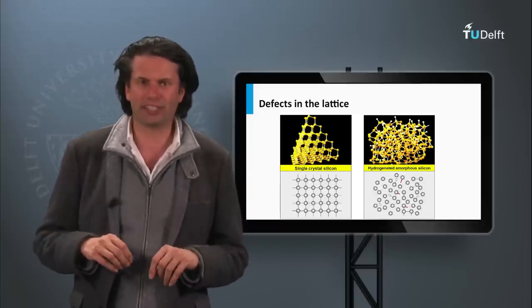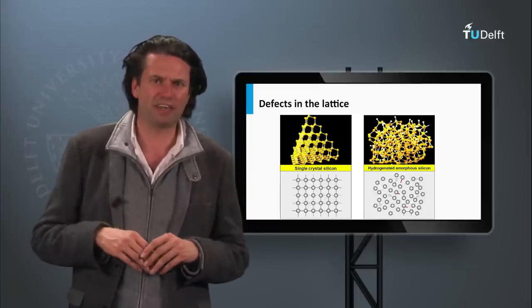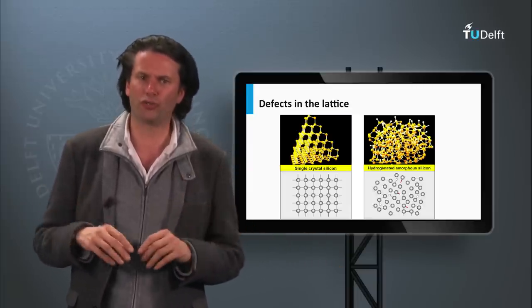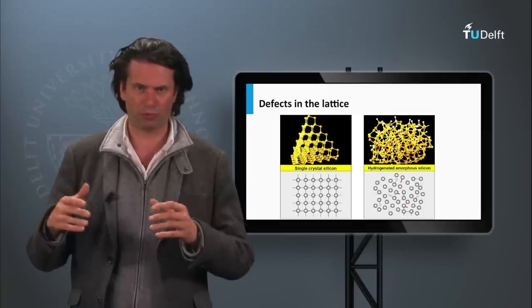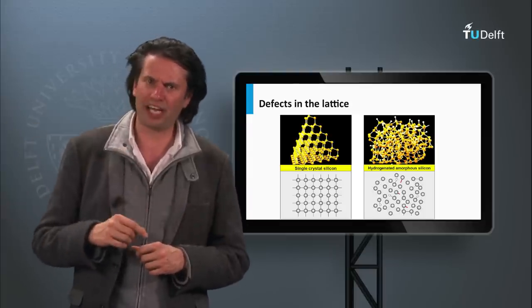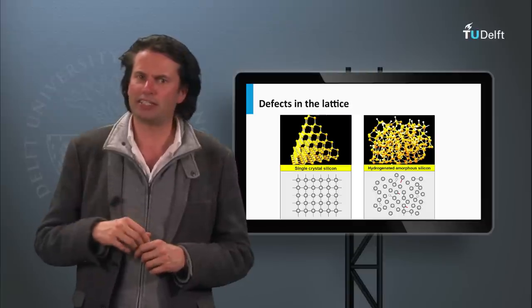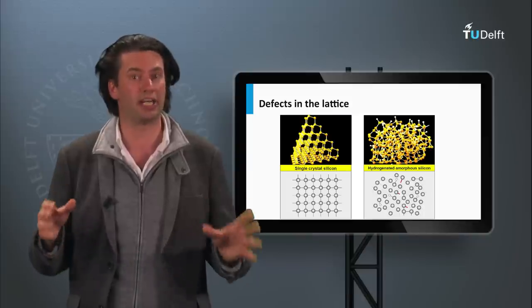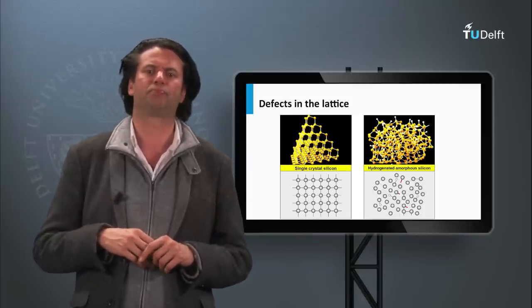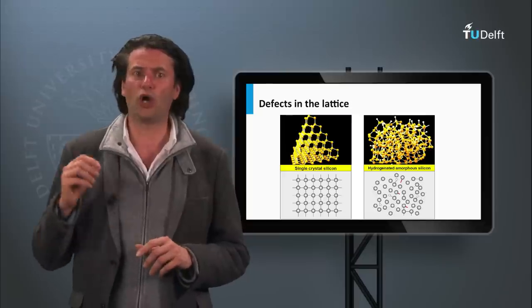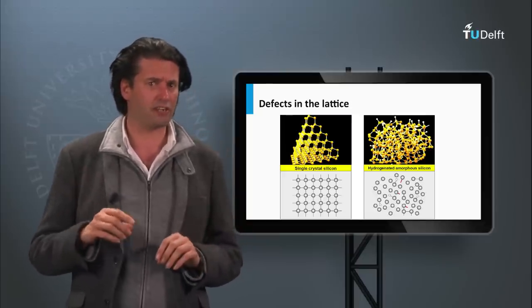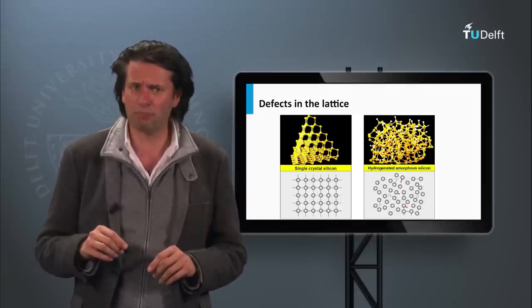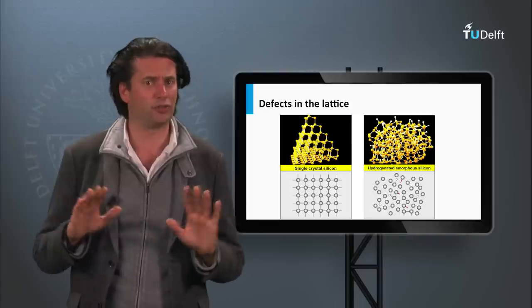Hydrogenated amorphous and nanocrystalline silicon films have a relatively high defect density compared to crystalline silicon. Due to the disordered structure, not all valence electrons are able to make bonds with neighboring atoms. These so-called dangling bonds can act as defects, meaning that the lifetime of light-excited charge carriers is limited by Shockley-Read-Hall recombination, which controls the diffusion length. The recombination is so high that the diffusion length of charge carriers in hydrogenated amorphous silicon is only 100 up to 300 nm, meaning that charge carrier transport in a thick absorber layer cannot rely on diffusion.